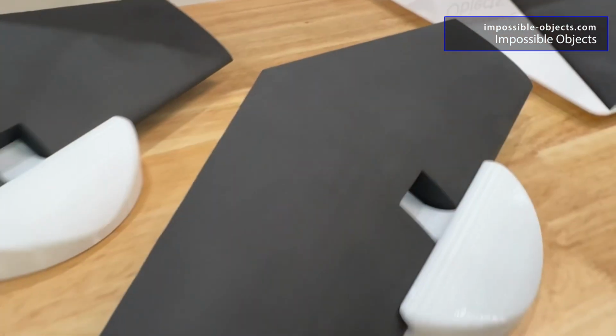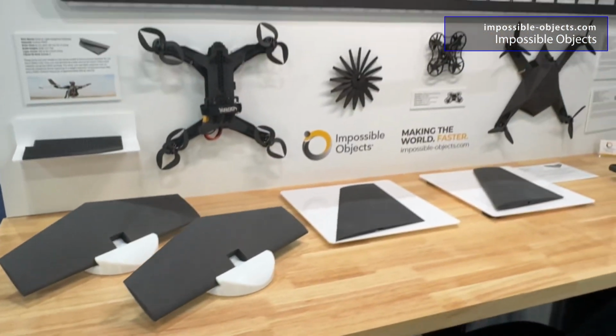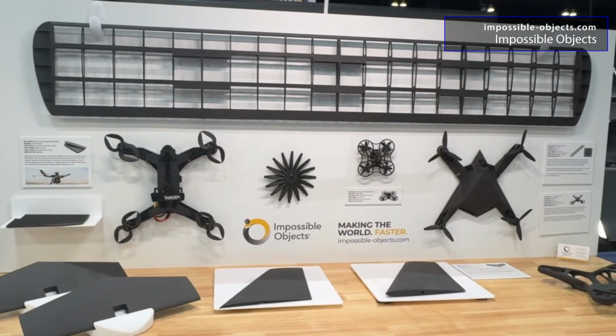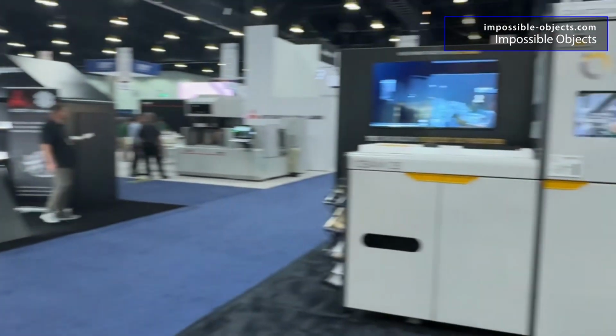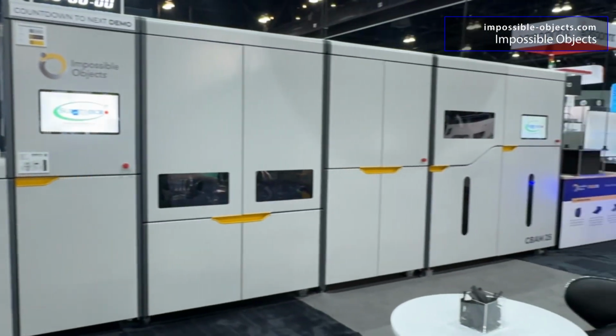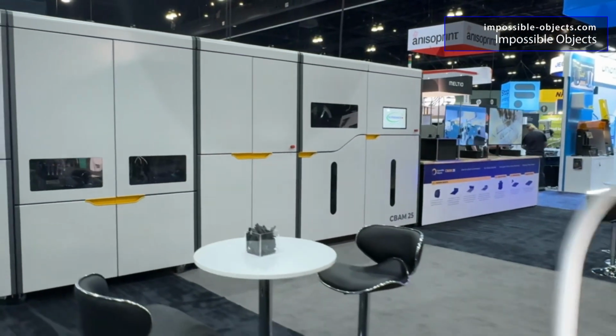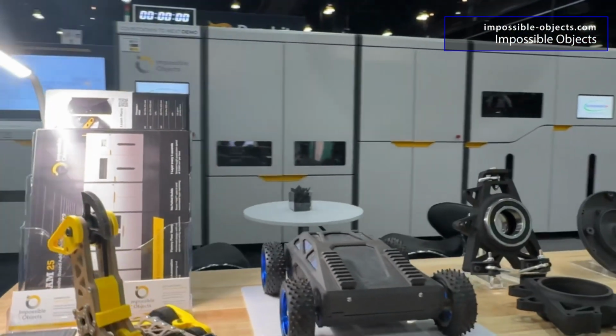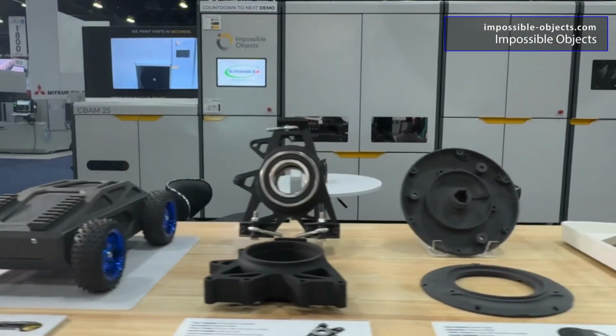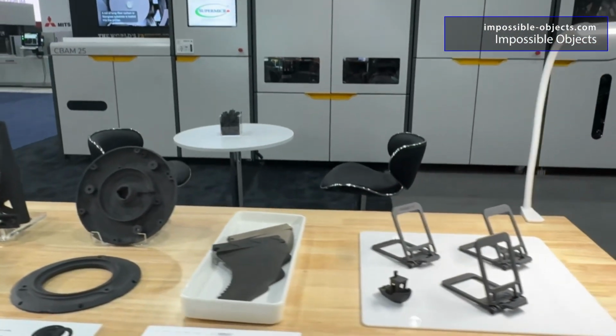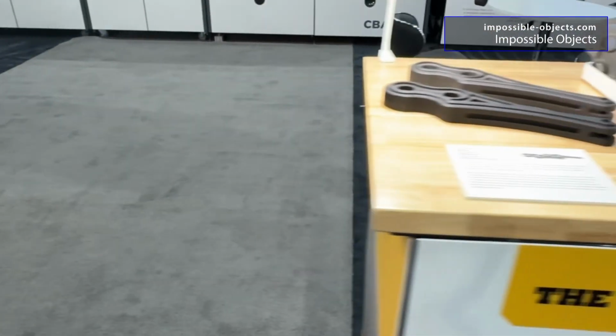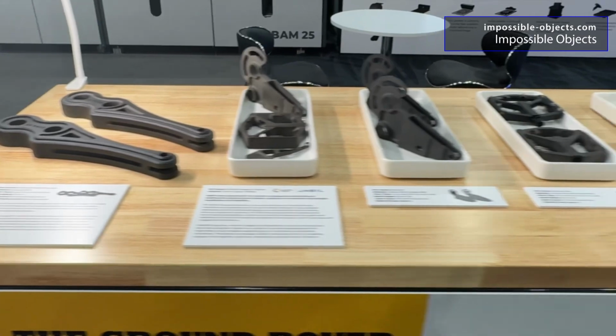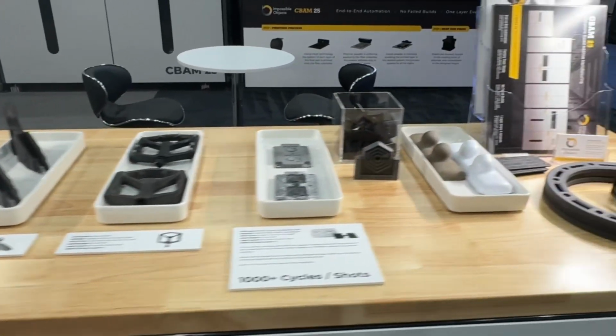Impossible Objects is targeting production work, and it has data showing that it's competitive with 6061 aluminum and conventional carbon fiber composite layups. For example, the cost per part is well below the current threshold established by aerospace industry and DoD specs. And for part strength, it showed that CBAM 25 can match that of 6061 aluminum while producing a part that weighs 50% less.